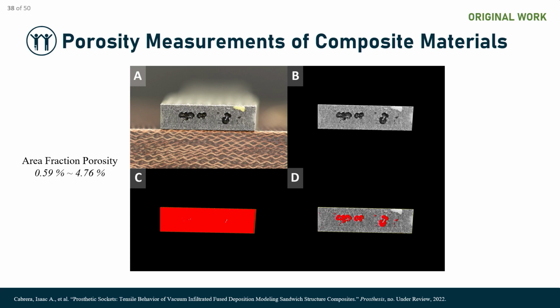We were interested in quantifying, in all our samples, the true amount of porosity. Those images I showed you previously are a little bit biased, right? Because it's where they broke. Of course, if they're going to break on the pores, you're going to see them in every image. But we wanted to see what was the true amount of porosity in our samples.